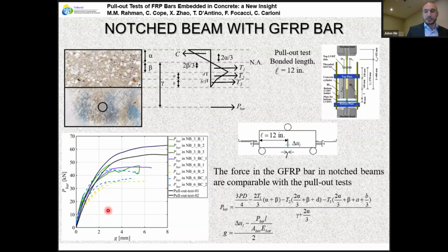And why is this important? Because there is a lot of discussion. How can I measure the relationship between the opening of the crack and the force in the bar in my beam in the field? Well, you don't need to do any tests. You can use a pull-out test, because at service load, when the load is not more than 35 kilonewtons, the slip of the bar, and therefore times 2, the opening of the crack, can be obtained from a simple pull-out test without any fancy test.